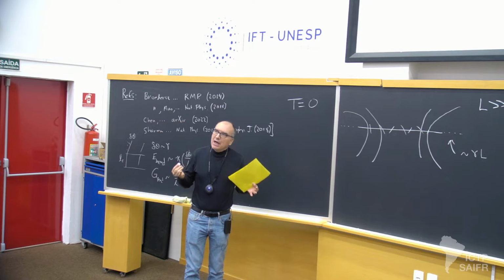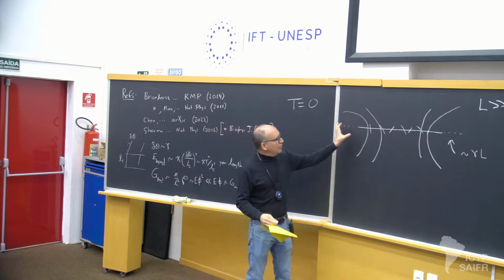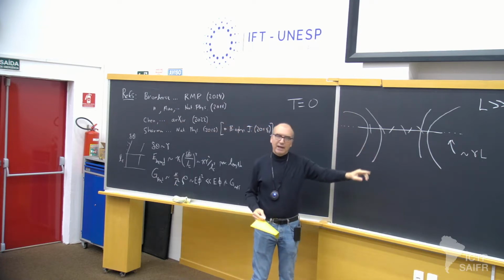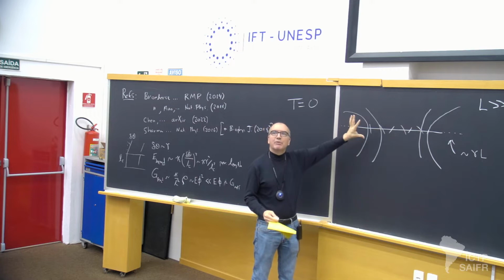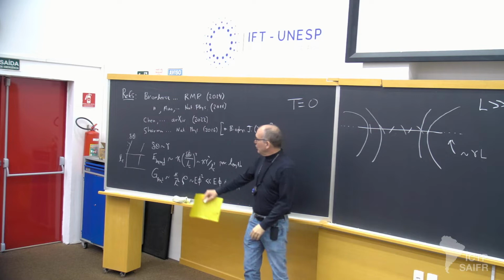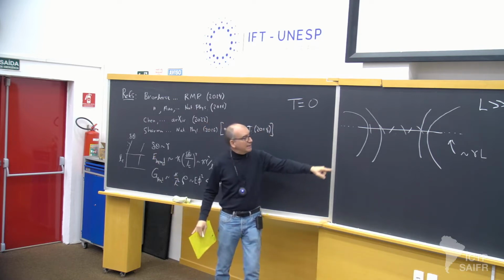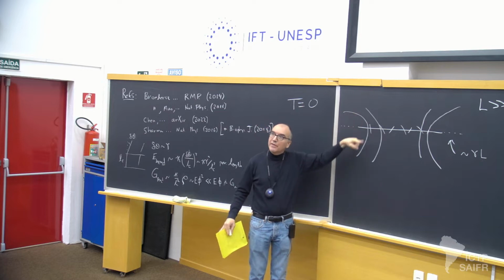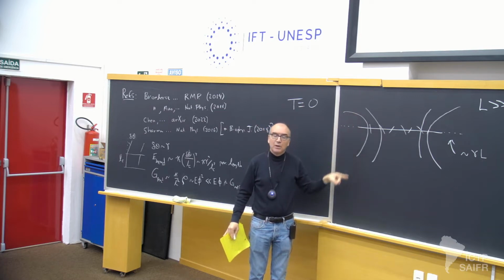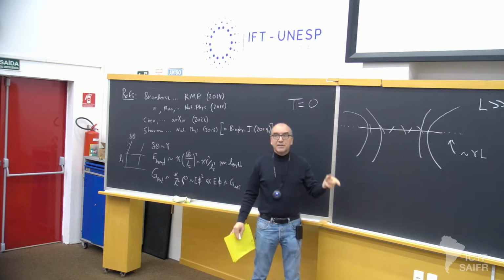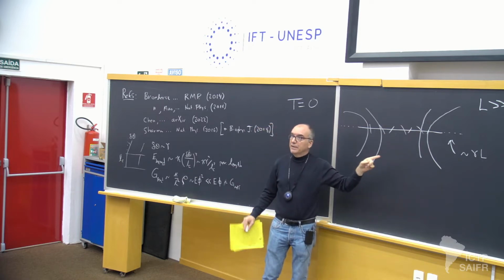And that's a big problem, because in the limit of high molecular weight, I'm taking a huge section of the network and deforming it massively. Not in a way which only depends on the strain, but also depends on the molecular weight. That means that even the bending energies associated with this get huge in the high molecular weight limit.